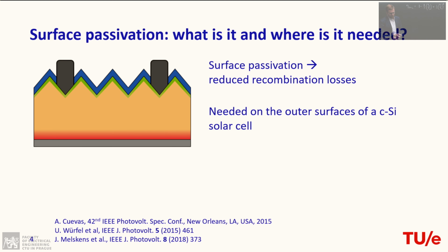So let's zoom in a little bit more. Surface passivation, I already mentioned it. So what is it now really? What you see here is a very basic diagram of a crystalline silicon cell. On the back side, you see a slab of aluminum over here. Then you see some, let's say, reddish zone over here, which is the so-called back surface field. The aluminum acts as a dopant when it diffuses into the silicon. And on the front side, we have some emitter, and then silicon nitride usually, and contacts in between.